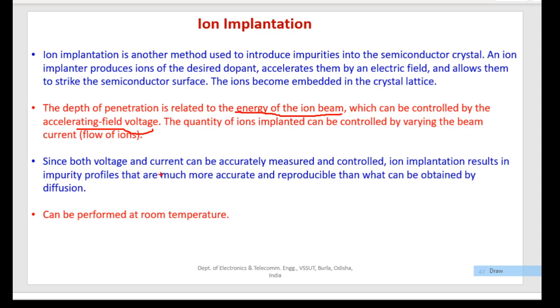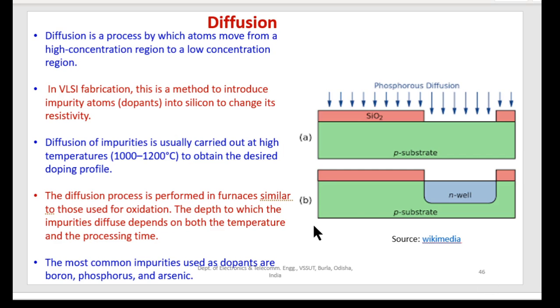Since both voltage and current can be accurately measured and controlled, ion implantation results in impurity profiles that are much more accurate and reproducible than what can be obtained by diffusion. So this process gives us more controlled, more accurate and reproducible impurity profiles within the substrate area. So this seems to be a bit more beneficial than the previous method, that is the diffusion method.